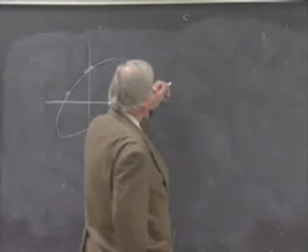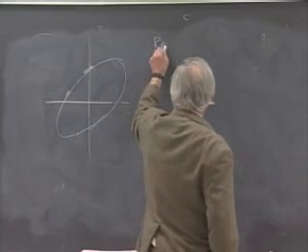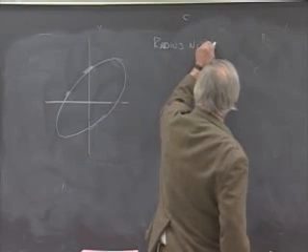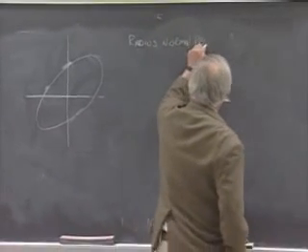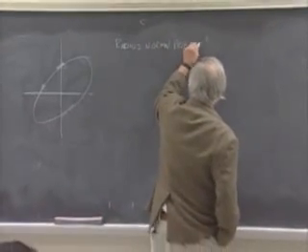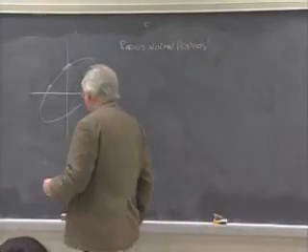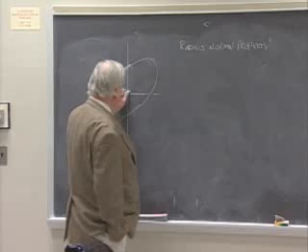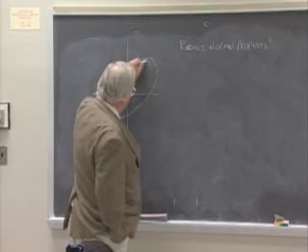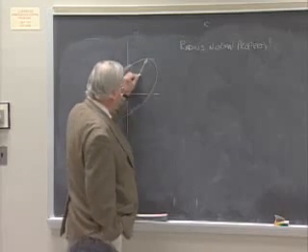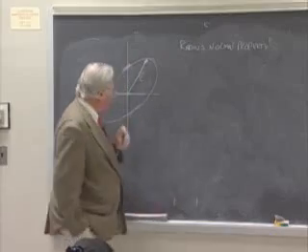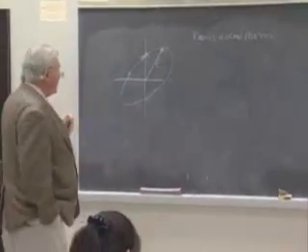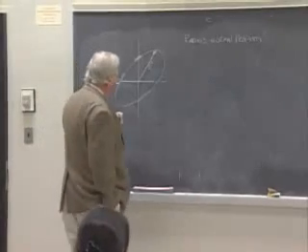Okay, this is something that's called the radius normal property. And what it says in words is that if you pick a particular direction relative to the quadric, we know that its length is going to be inversely proportional to the square root of the value of the property.